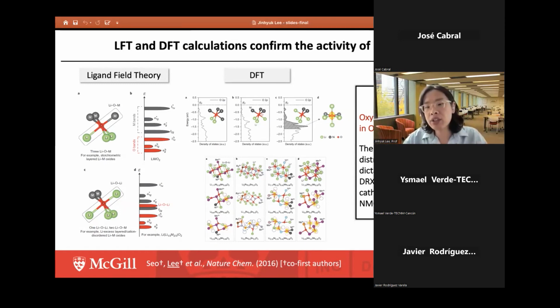control the population and the spatial distribution of this particular lithium-oxygen-lithium state to determine the oxygen redox activity of the lithium DRX materials and also other types of lithium-excess transition metal oxide cathodes, such as layered lithium-excess NMC cathodes, basically because they share the same crystal structure overall. They're the broader structure, so the same principle applies. So this was the basic understanding of how this mixed transition metal and oxygen redox process can happen in these cathode materials. And this paper has been cited almost already above a thousand times, and has become a very important paper in this field.